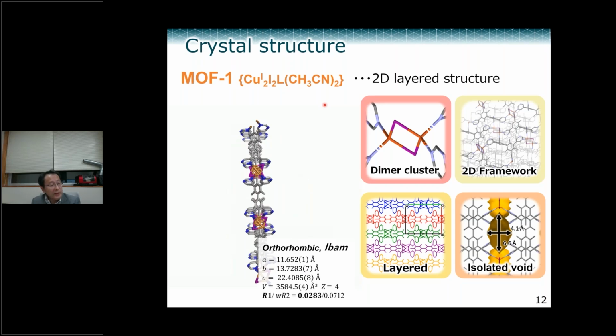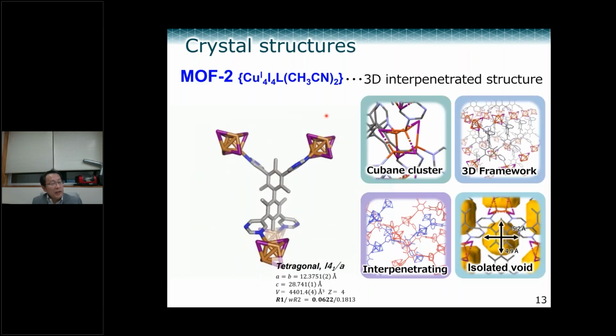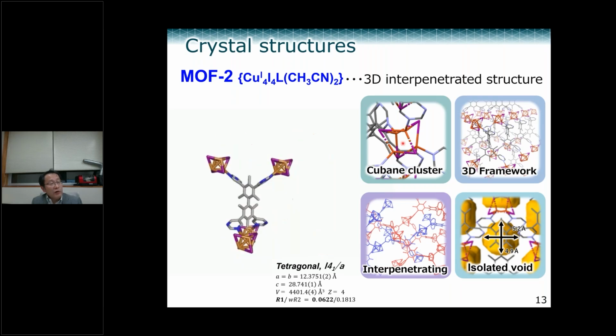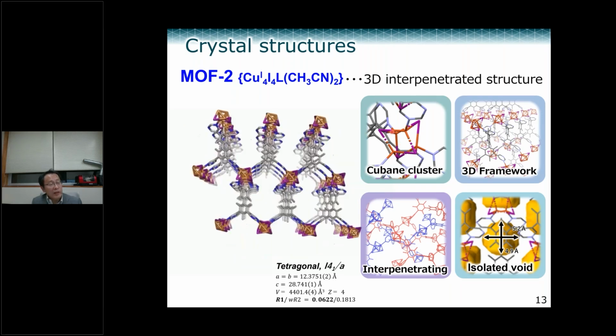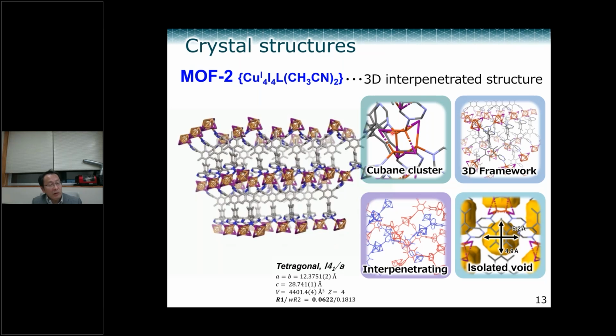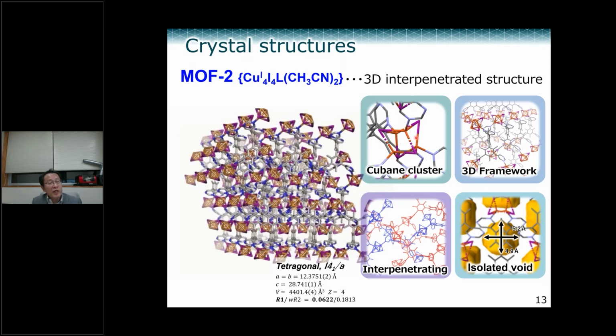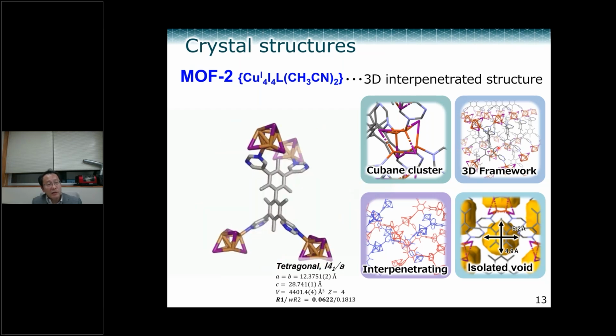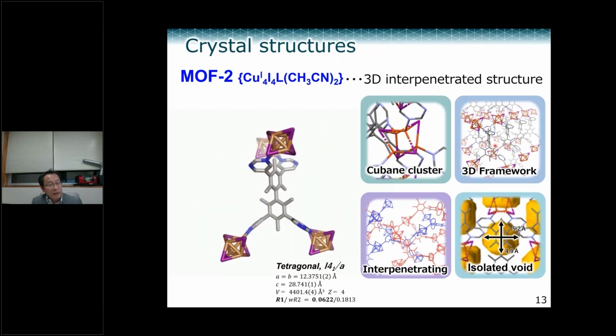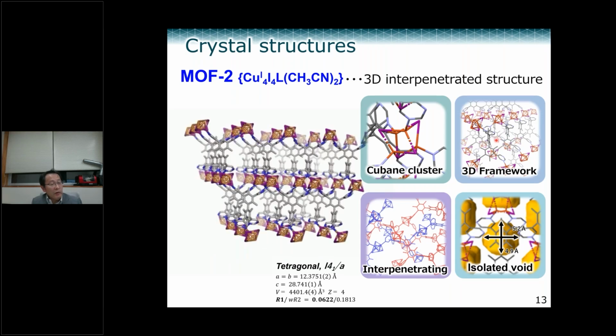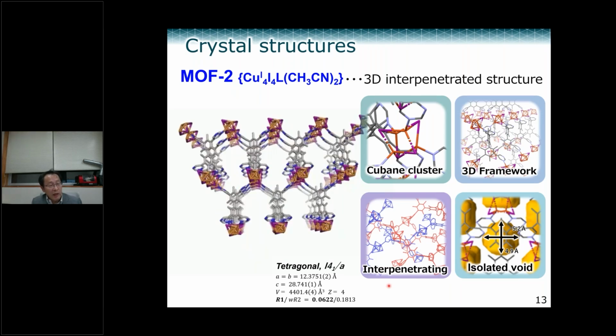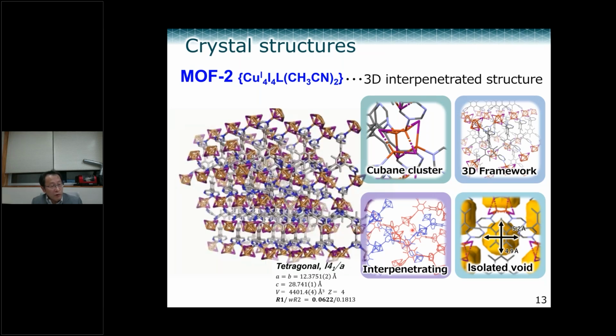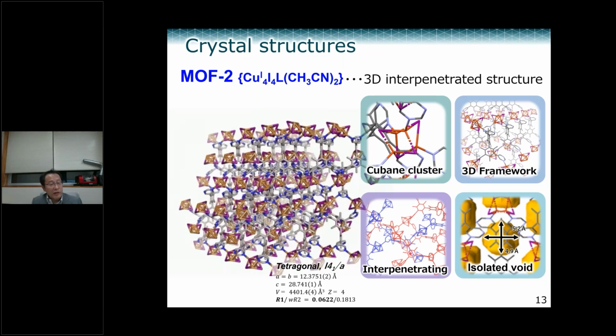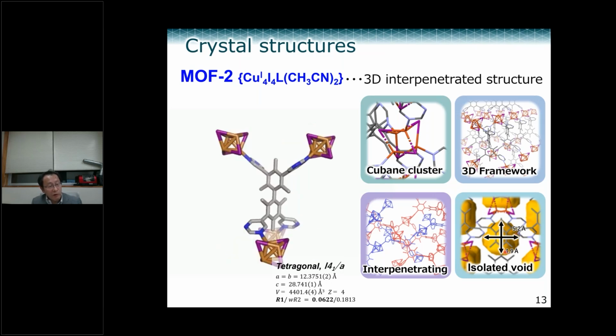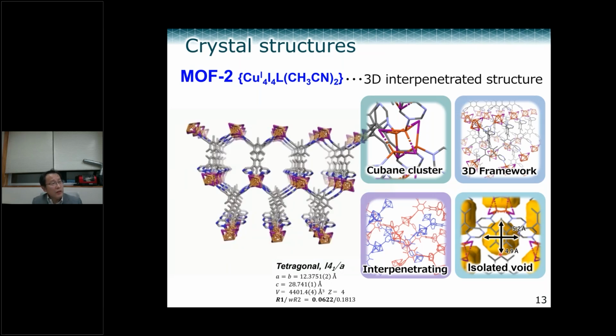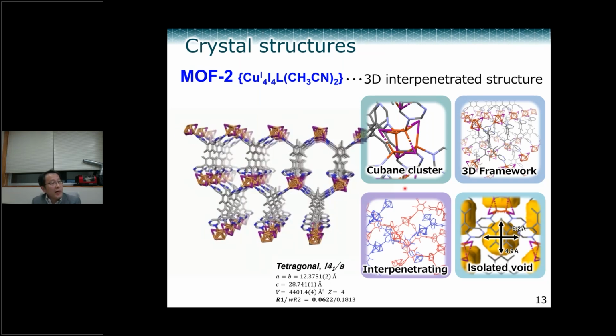Okay, then what about the MOF2 structure? In this case, the connector is a copper iodide cubane. The last one was Cu2I2, but in this case it is a Cu4I4 connector. Another feature is that this is a 3D framework rather than a 2D framework, totally different from MOF1. This 3D framework is interpenetrating, doubly interpenetrating. This MOF2 also has an isolated pore, with dimensions of about 5 angstrom by 5 angstrom. So now we know the structure, and we call this MOF a 3D MOF.